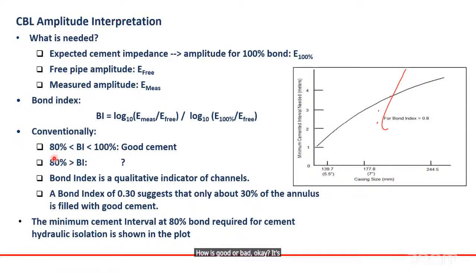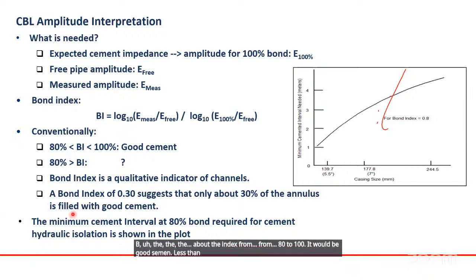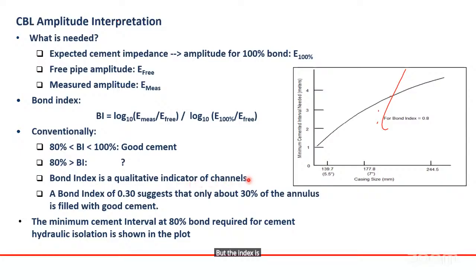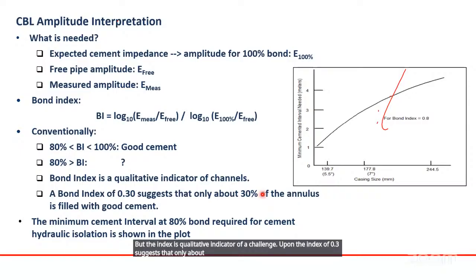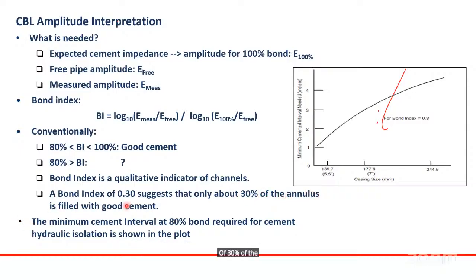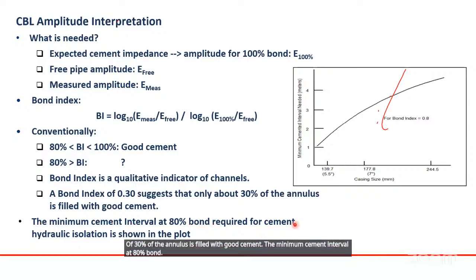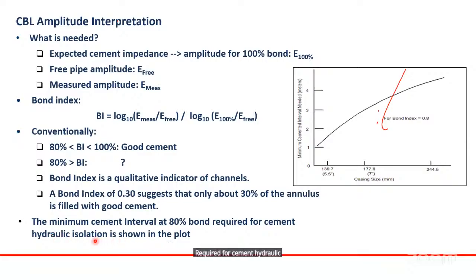Conventionally we are looking for a bond index from 80 to 100. It will be good cement. Less than 80, it is questionable. Bond index is a qualitative indicator of a channel. A bond index of 0.3 suggests that only about 30% of the annulus is filled with good cement. The minimum cement interval at 80% bond required for cement hydraulic isolation is shown in the plot.